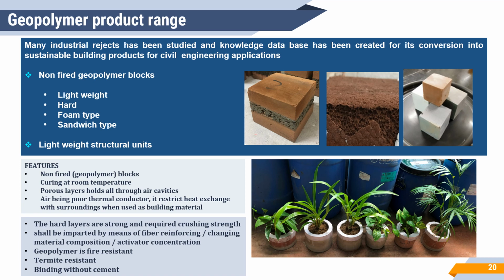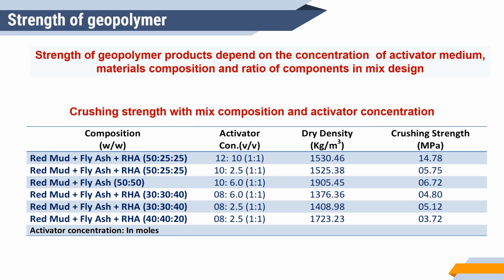The studies identified good synergy among aluminum industry rejects, steel industry rejects, as well as biomass-based rejects such as rice husk ash, bagasse ash, and corncob ash, etc. for development of green building material based on geopolymerization. The three simple steps of mixing, molding, and curing make the geopolymer matrix. Mixing for alkali activation of raw material is most crucial, since not all alkali activated materials make geopolymer products. To make geopolymer matrix, low calcium aluminosilicates are generally preferred.